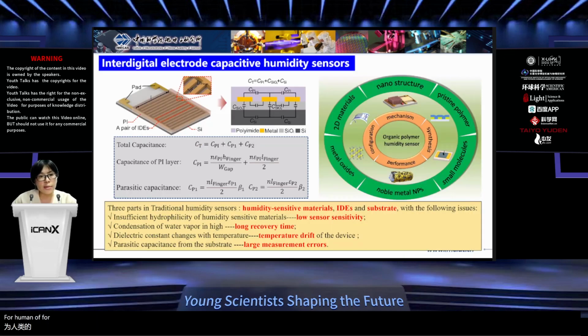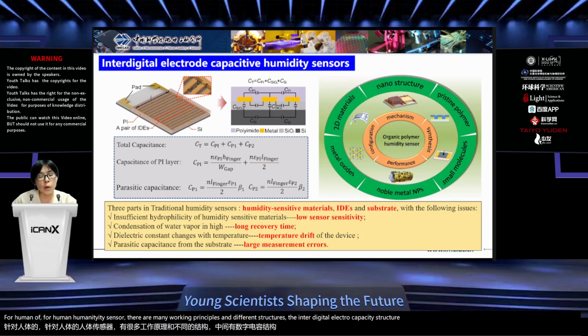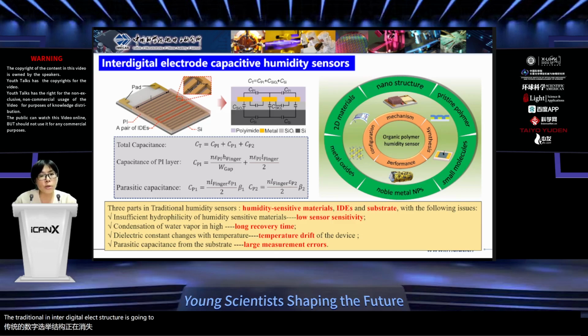For humidity sensors, there are many working principles and different structures. The interdigital electrode capacitive structure is the most commonly used. The traditional interdigital electrode structure is prone to introducing parasitic capacitance from the substrate, which affects the measurement results of the sensors. In addition, traditional humidity sensing materials such as PI photoresist may have low sensitivity due to their insufficient hydrophilicity. At the same time, they have semi-closed nanostructures, which may lead to long-term absorption and desorption of water molecules. Therefore, the response time and the recovery time of the devices might be long.